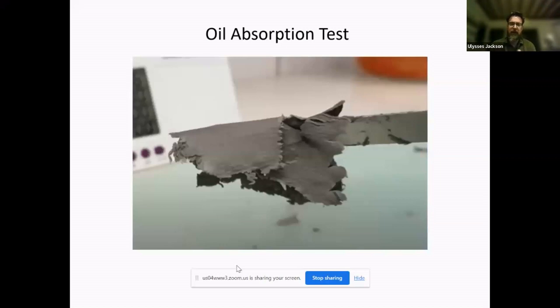We would say, oh, this pigment is similar to cobalt blue. What did we do in acrylic for cobalt blue? Because they should have a similar need for binder demand. Then if you took a pigment at this level of oil absorption and you add a tiny bit more oil, what will happen is it will actually start to space out those pigment particles and give lubricity, which allows the paint to flow, and you actually have a functional oil paint.